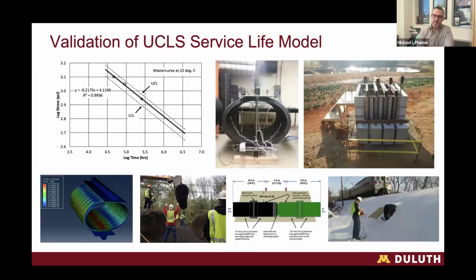And the previous research, then, what we did is we developed the model, and then we validated that model in some extreme installation conditions to see if it played out in real life. And what we found is that the model perfectly fit the pipes that we tested. So we had multiple full-scale pipes that were tested. In the upper right-hand corner, you can see a simulated burial chamber where we simulated 100 feet of fill on a pipe that was installed in that concrete chamber. And then we also did a number of tests in the lab and some field testing as well to validate the model.